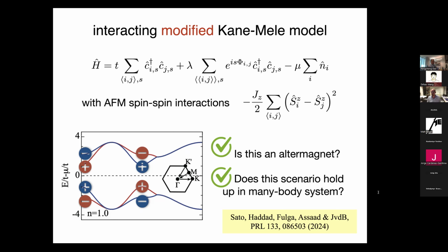Actually, there's another question from Nitin Kashwa. Do you expect anything interesting from hole or electron doping of altermagnetic insulators, like superconducting tendencies? Oh, okay. That's an exotic question. I would say a priori not. Doping any antiferromagnet is interesting, and getting them metallic is interesting, especially spin one-half, of course. But actually the cuprate La2CuO4 is an altermagnet, only the spin splitting is really tiny. It has to do with the rotations of the octahedra.